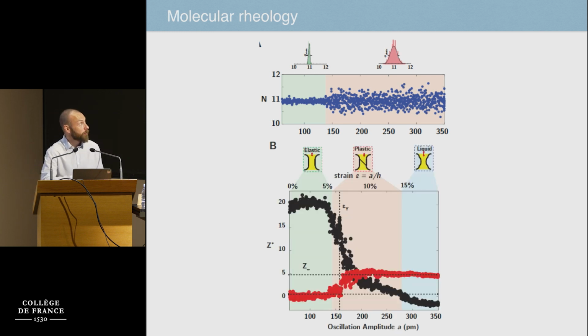And in parallel, what was interesting was of course studying the mechanical response. So in this regime of small oscillation amplitude, the mechanical response is only characterized by a stiffness. So it is behaving like a solid, let's say. When you arrive at this critical value, you observe a drop in the elastic term and an increase in the dissipative part. And then when you increase even more, you observe that the dissipation is quite constant, while at a certain point you observe even a change and a negative elastic term.